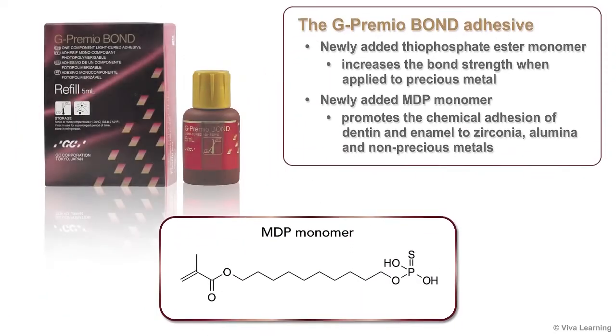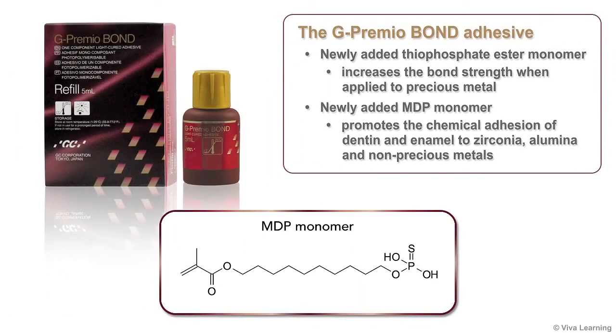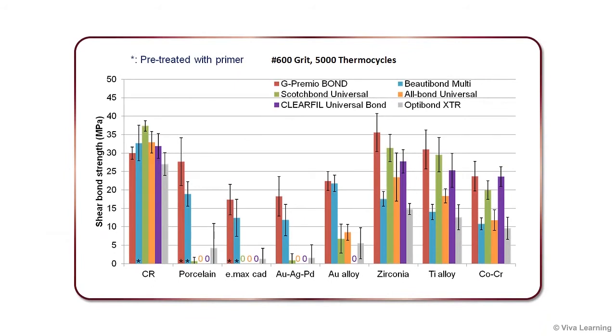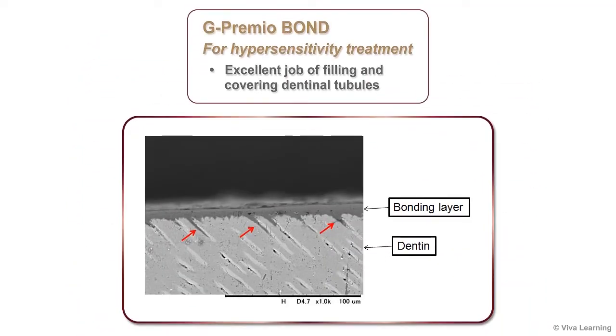The G-Premio Bond adhesive contains a newly added thiophosphate ester monomer that increases the bond strength when applied to precious metal, and a newly added MDP monomer that promotes chemical adhesion of dentin and enamel to zirconia, alumina, and non-precious metals. This graph shows the shear bond strength achieved by G-Premio Bond when applied to various materials, compared to the shear bond strength of other adhesive products. In addition, for hypersensitivity treatment, G-Premio Bond does an excellent job of filling and covering dentinal tubules.